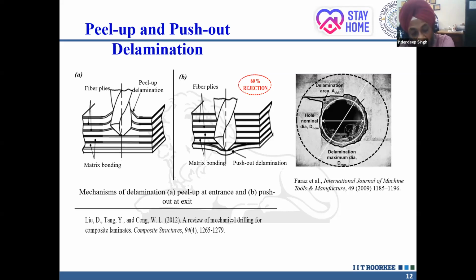Similarly, when the tool will be in contact with the hole for a long period of time during the hole making operation, the heat buildup will be high. Why will the heat buildup be high? Because the fibers may be poor conductors of heat and the polymers are known to be poor conductors of heat. So the heat will be built up in the machining zone, which will not be dissipated properly. And if we are making a hole in 35 to 40 minutes time, matrix burning may take place.